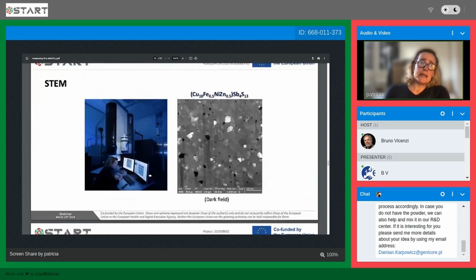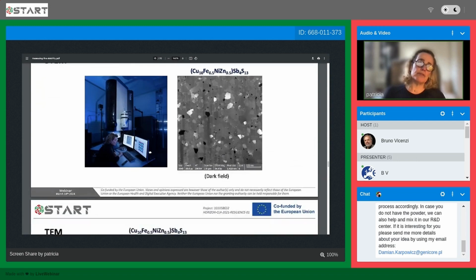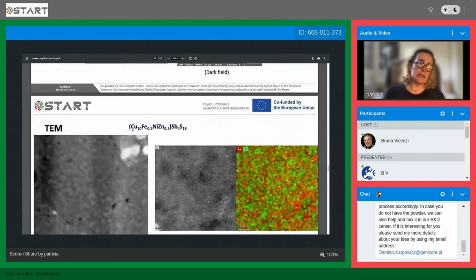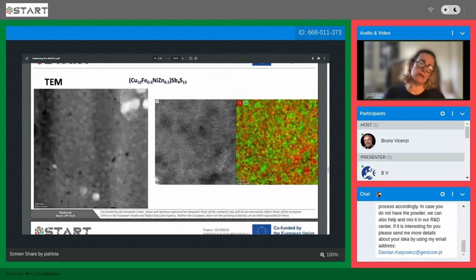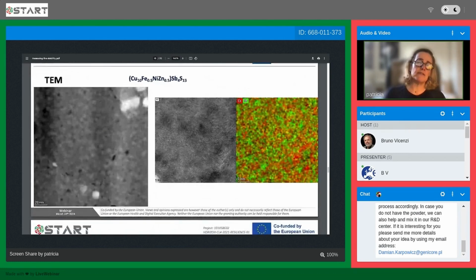What we have done next was to use scanning transmission electron microscopy. And here you see that again, you have all these holes, things that look like pores, but we were not totally sure of what they could be. But then I will show you some results. An additional aspect in which TEM is certainly one of the few techniques that can provide information is that when we anneal the samples, we see a very fine decomposition, or a very fine microstructure in the order of 10 nanometers.